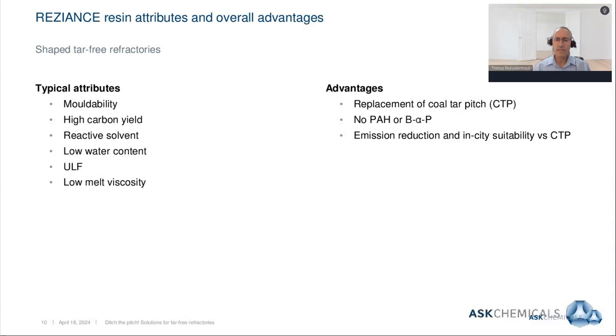The typical advantages that phenolic resins bring is that it has been proven as a viable alternative in the place of coal tar pitch. It does not contain any of the polycyclic aromatic hydrocarbons or benzoalpha pyrenes that pitch contains. In other words, the toxicity profile of a phenolic resin is significantly lower than pitch. And then lastly, if you think of emissions from coal tar pitch compared to phenolic, significantly lower emissions or toxic emissions from a phenolic resin, which is specifically important if you think of factories or production sites that are in close proximity to suburban areas. Next slide, please, Peter.